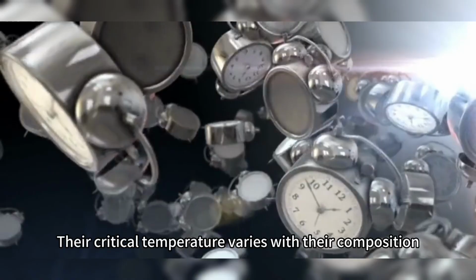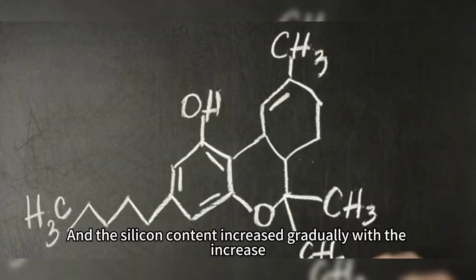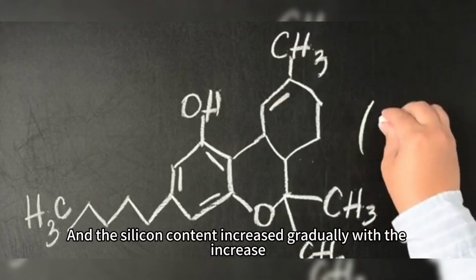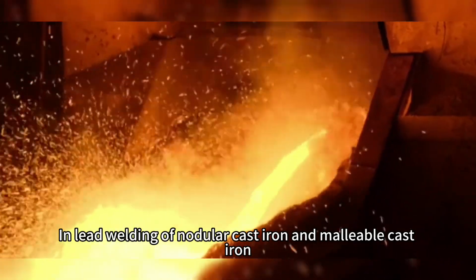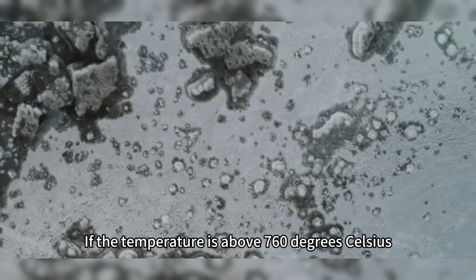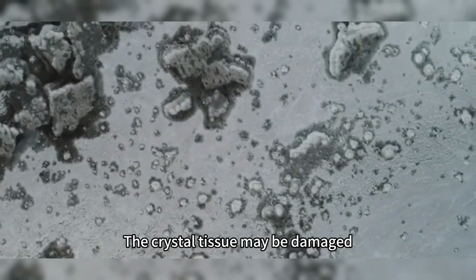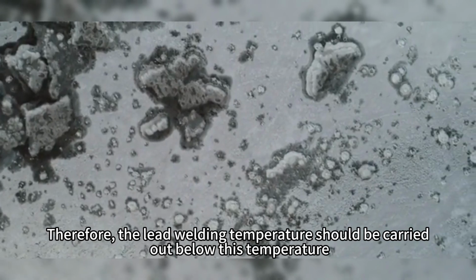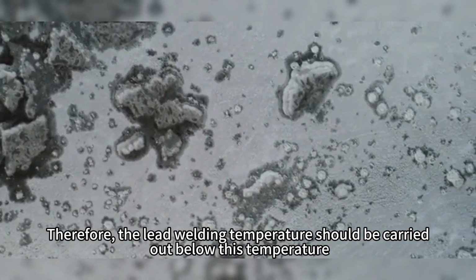Their critical temperature varies with their composition, and the silicon content increases it gradually. In braze welding of nodular cast iron and malleable cast iron, if the temperature is above 760 degrees Celsius, the crystal tissue may be damaged. Therefore, the braze welding should be carried out below this temperature.